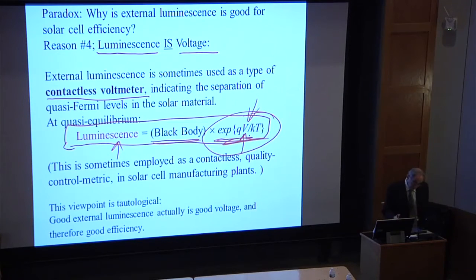Now, to give an idea of the degree to which this is accepted in the industry, as a quality control metric in a factory, they'll put solar panels out in the field, and they'll take a snapshot with an infrared camera, and they should all glow in the infrared. And if they don't glow, you take that panel, it should not be shipped. There's something wrong with that panel. And so they use it for quality control. And so this viewpoint is somewhat tautological. Good luminescence is good voltage, and therefore it's a good thing to have.